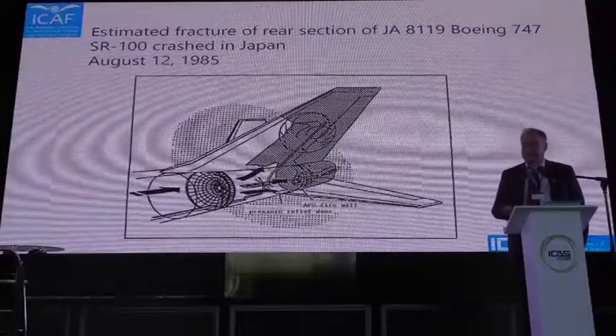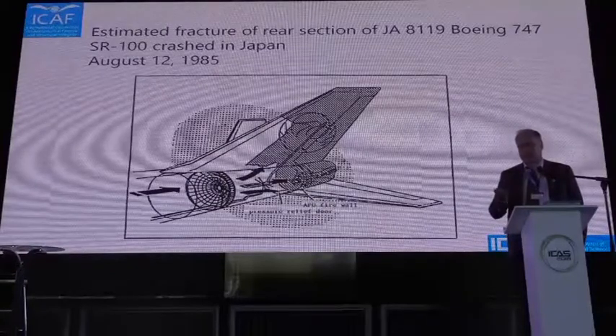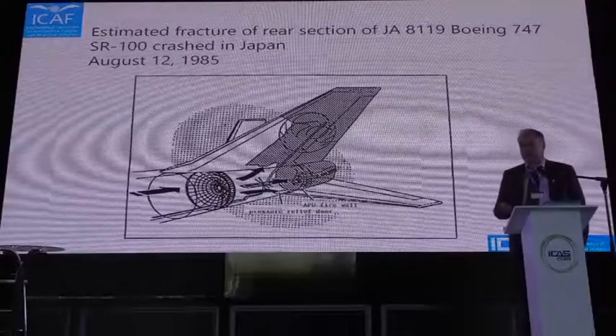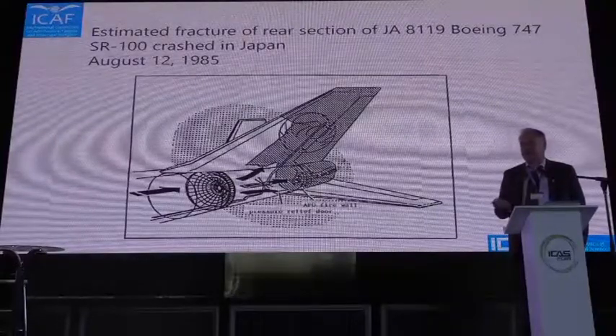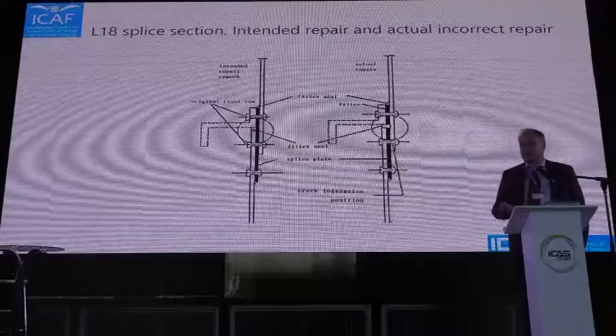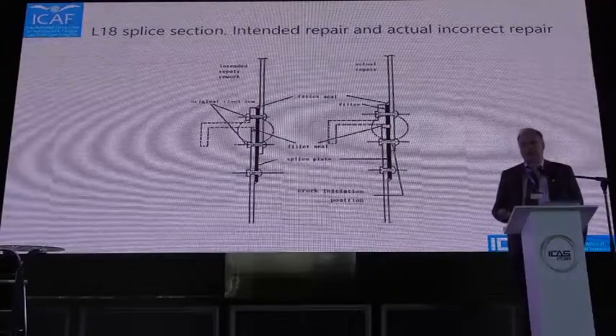The reason for this was that the plane had previously had a very bad landing, introducing damage in this bulkhead. So it was repaired according to what were correct regulations. However, the repair did not occur in the right way.